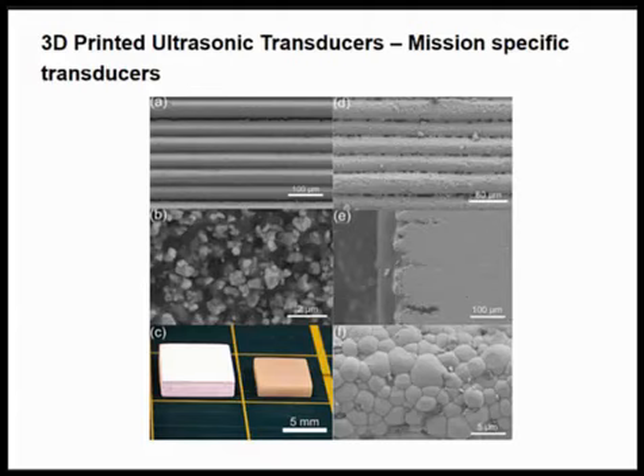You get nice kind of resin-rich areas and particle-rich areas. So that takes an awful lot of work to get to that point. You then do the firing, so yes, you get some shrinkage, but it's nice and uniform. You get nice kind of dense ceramics. You don't really see any effects of a layering apart from this kind of sub 100 micron indent occasionally. You get a nice dense ceramic at the end of it.